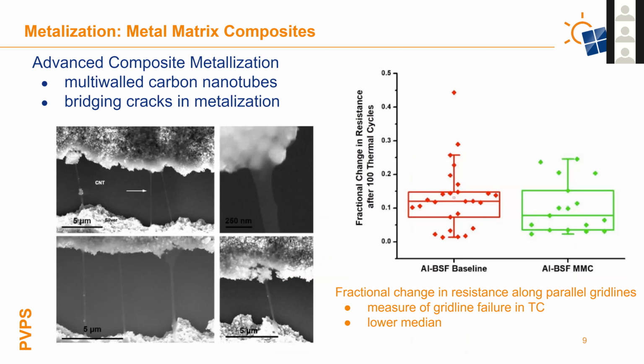Something new being discussed is metal matrix composites added to the grid lines, using multi-walled carbon nanotubes that can bridge cracks in metallization. If there's a fracture in your cell, that can cause a fracture in the metallization, which causes power loss as well as being a root cause of hotspots. So one way to potentially mitigate or correct these cracks is with these multi-walled carbon nanotubes, which can help self-heal cracks or electrically bridge them so you don't get the drop in power.